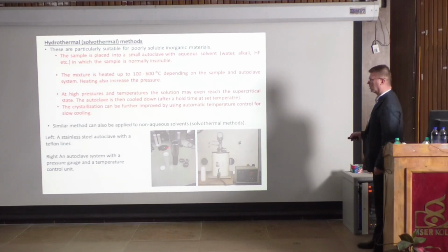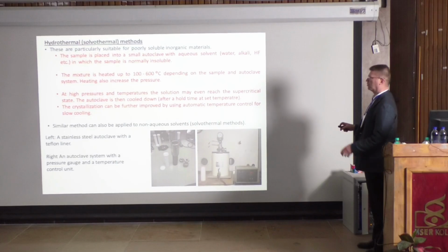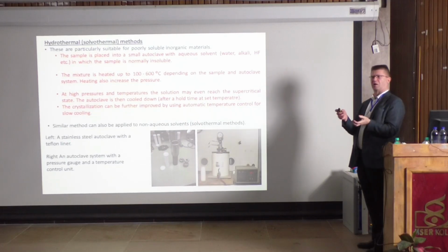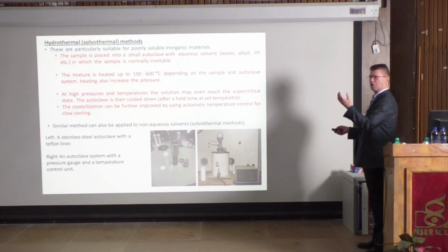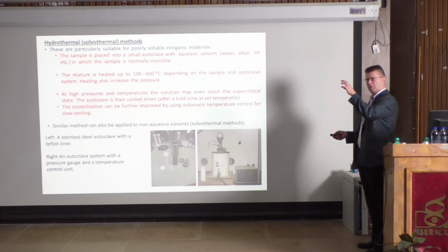So what happens in here is that now when you go and heat this mixture in a closed vessel, clearly up, much higher than the boiling point, it creates a big pressure. So now at the same time you have there in the solvent a high temperature and high pressure. That will force the components to dissolve, and then when you cool it down, what you do is you keep it there. You keep it like he was keeping 7 days. You can keep it 1 day or 2 days or so on. But the point is you keep it long enough that